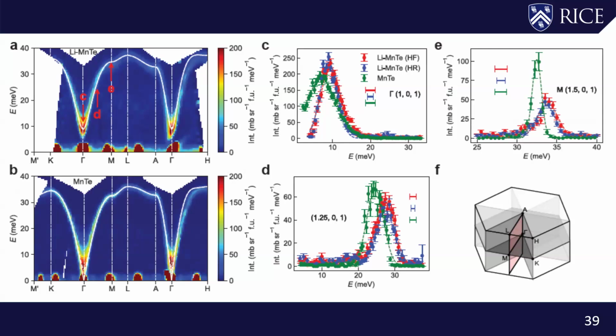But what's really surprising to us is that once you dope lithium, even though the total exchange coupling constant is reduced slightly, your magnon bandwidth, your magnon width, which is the lifetime of the system, actually increased dramatically, by roughly a factor of 2 or 3, as compared with the resolution limited case for the pure MnTe. In the pure MnTe, we can essentially think of the system as a local moment system, with a Heisenberg type of exchange interaction.